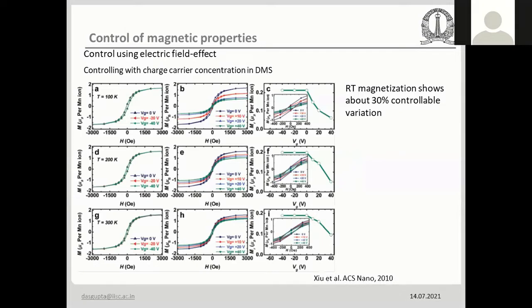And I think the top three pictures in the first row are measured at 100 Kelvin, then 200, and then 300 Kelvin. So at least at lower temperature, at 100 Kelvin, the change is quite drastic. As you can see, it is more or less going from 0.2 Bohr magneton per manganese ion down to 0.05. And at room temperature, the control is 30%. So this is field effect, or electric field control of magnetization.